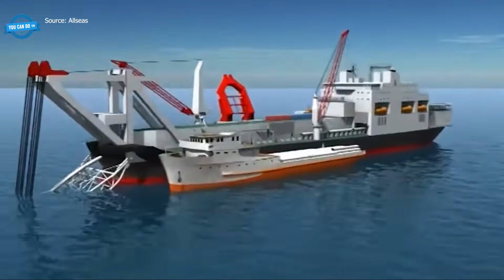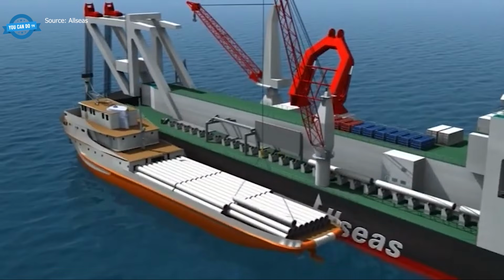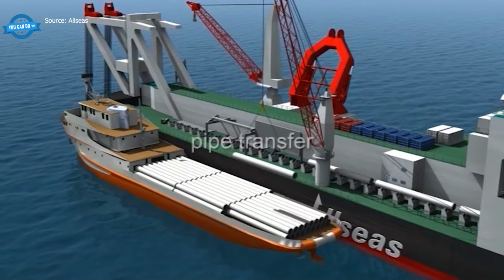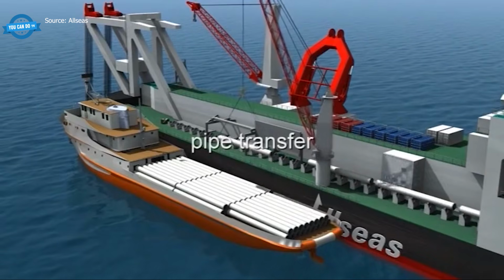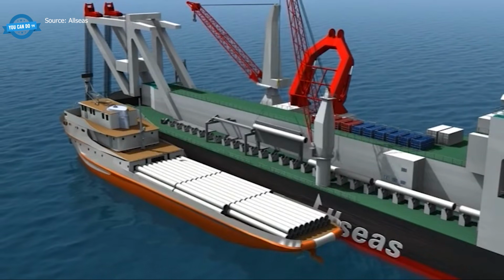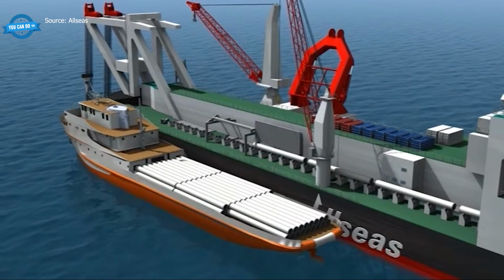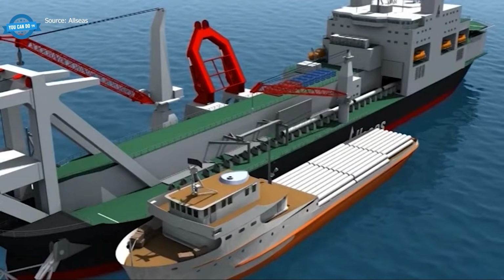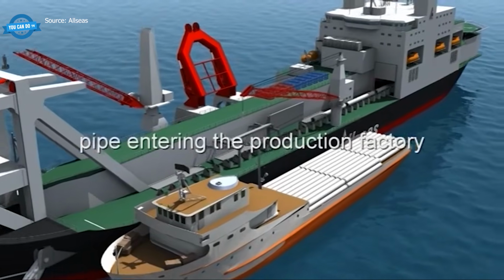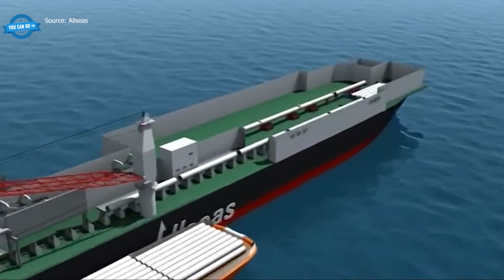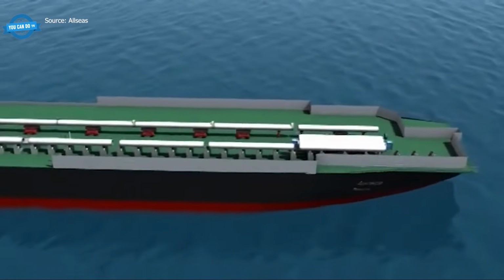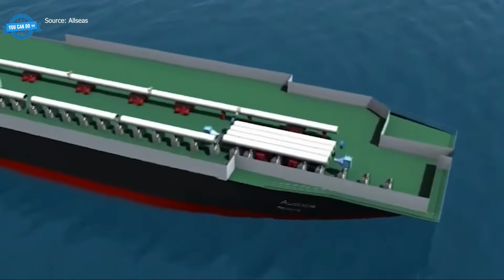On a specific S-lay vessel, the full cycle takes only minutes per joint. One specialized pipelay vessel has been optimized for pipelines of small to large diameter in all water depths. Pipe sections are transferred on board from a supply vessel, beveled, preheated, aligned, and welded through the standard root-hot fill cap sequence.